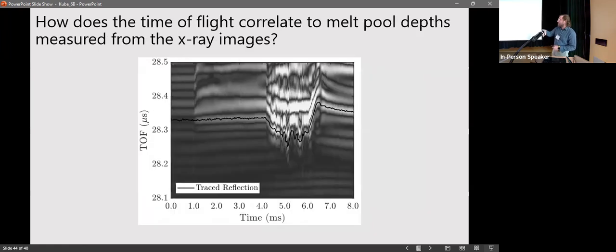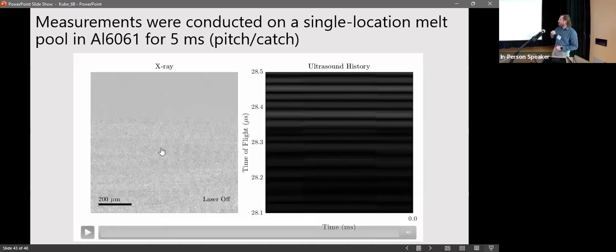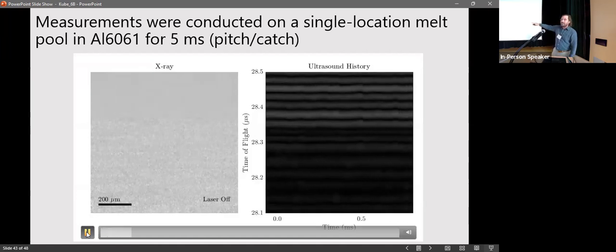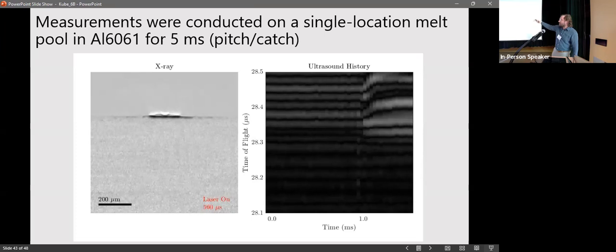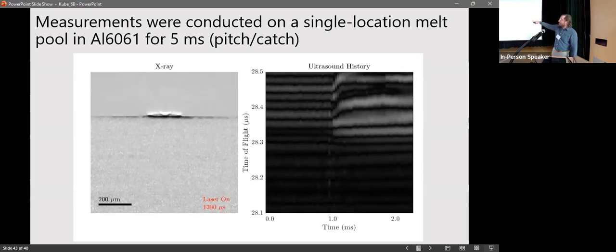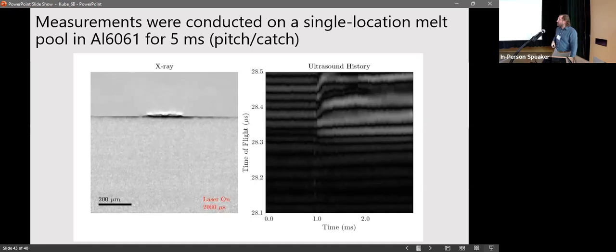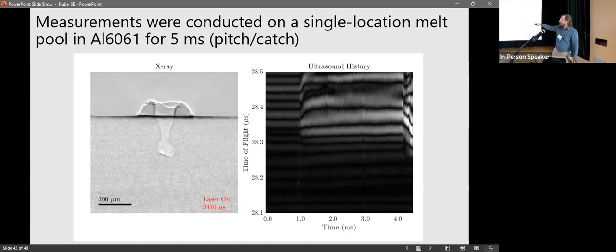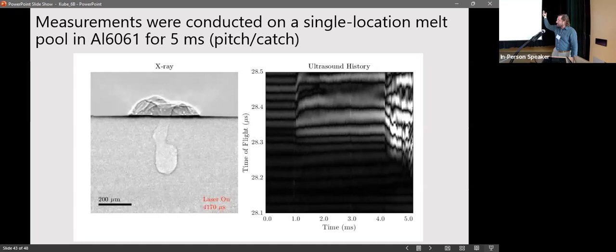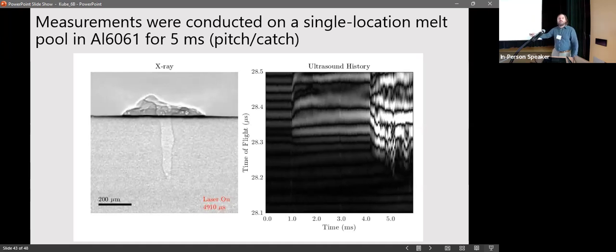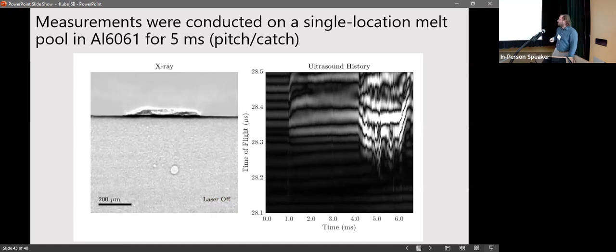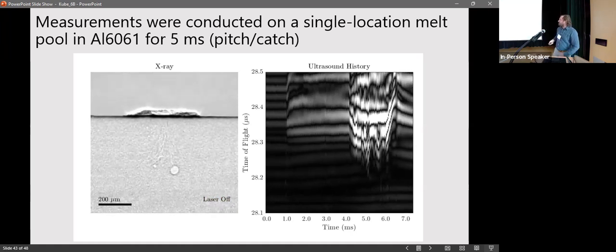So this is a single point melt pool on aluminum. And so on the left-hand side, you're going to see the X-ray video. Each of these frames is the current snapshot. We have a conduction stable melt pool at this point. The laser's on. The laser's going to be on for about 5 milliseconds. There's a nice melt pool, and then you get a keyhole. So the laser energy drives the material down. It boils some of the liquid metal out of there, and then you get the solidification.